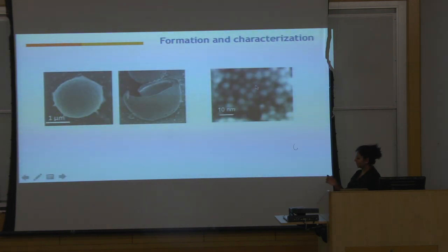Over here, the shell wall does consist of many, many layers of nanoparticles already stacked. Usually we found that the thickness of the wall is between 10 to 20% of the diameter, and that scales with the size of the shell. One of our collaborators has been doing this, and they have found a little bit lower than what we see experimentally, but about 10% or so.